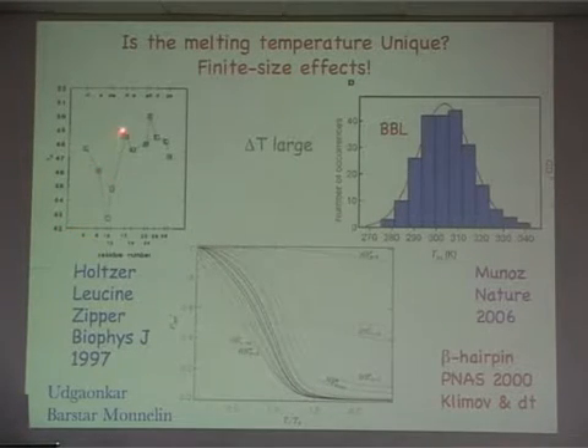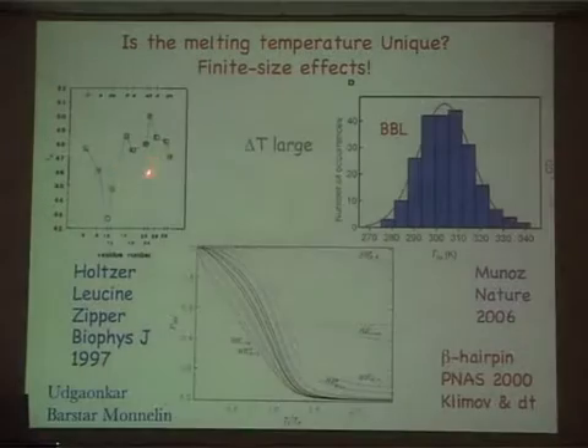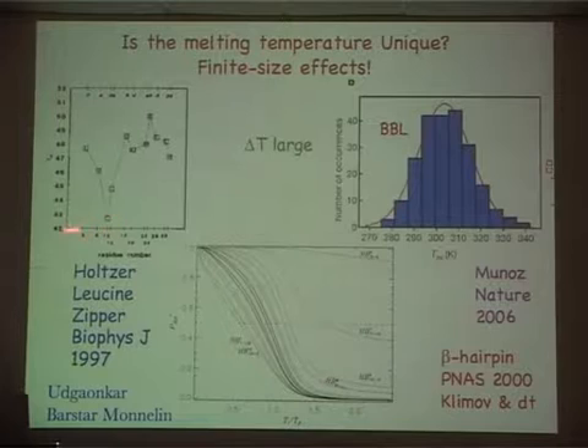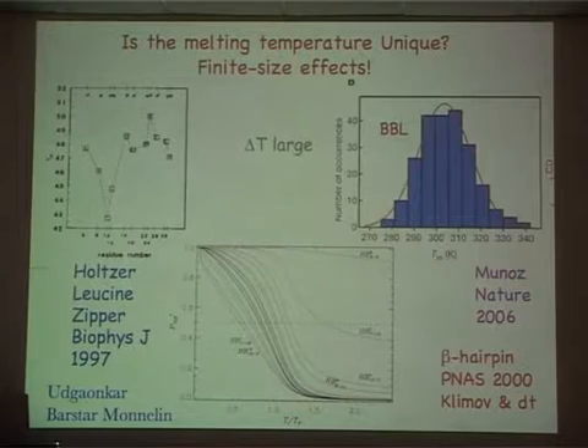For leucine zipper, it's a melting temperature as a function of residue number obtained by one-dimensional NMR experiments. And you can see this is not a constant. It varies from the smallest number of about 42.5 degrees to about 50 degrees. There's a 7-degree dispersion, which is not small, given that the global melting takes place somewhere here, say. So this says that ordering depends upon where you actually look. And this is quite consistent with what I showed you earlier in a kinetic sense, that you can only ask questions of probability, not certainty, which reflects the underlying heterogeneity in the protein conformations.